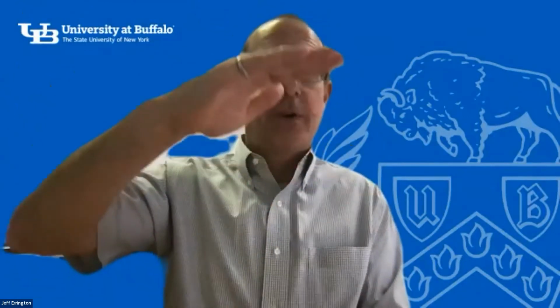Right. So in its most general form, you have the substrate or surface that you're interested in on one end. In the spreading type of approach, what you put at the top of the sandwich is a hard wall, so the fluid doesn't want anything to do with that interface. As you introduce fluid to the surface, it naturally wants to go to the substrate of interest, and as you add more water, or fluid, to the system, the fluid grows from the surface. So is this done at a constant chemical potential, or do you vary the chemical potential?